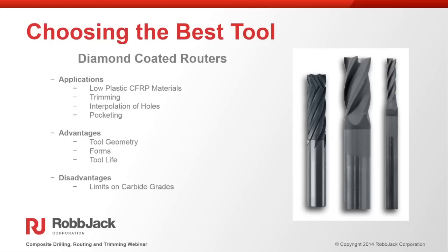When you get to the diamond-coated tools, you have the same availability of geometries, because anything you can grind on the carbide, you can diamond coat as well. Typically, the diamond-coated tools are used in composites for trimming in heavy applications where the carbon fiber is a little bit easier to cut, because if it's a very difficult carbon fiber, it'll tend to delaminate that diamond layer. So where we said that diamond coated and PCD is excellent for drilling, on the trimming side we've seen more successes with the PCD versus the diamond coated, but we do have a lot of customers that use our diamond-coated tools for trimming applications.